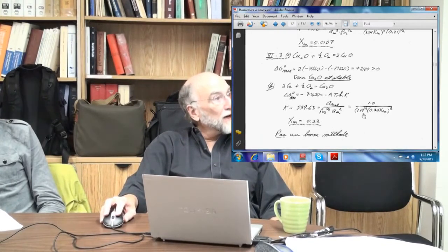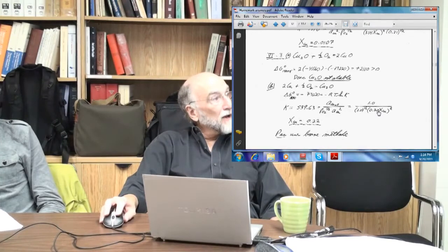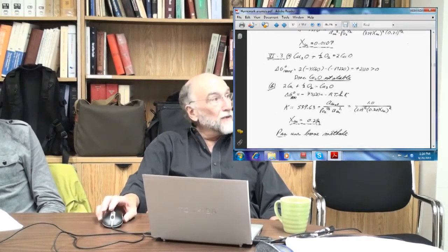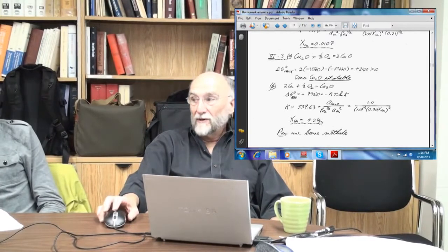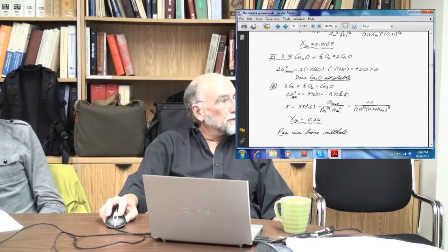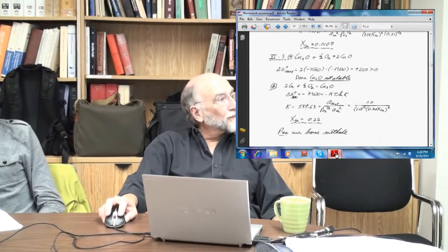The PO2 is 1 atmosphere, and this then allows you to calculate the activity of copper at equilibrium, which is gamma times X, so X is 0.22. So that's the minimum. You can continue to bubble the oxygen forever. You will never get the copper content below that. Obviously a pretty crummy method if you want to get copper out of here. These are really simple.